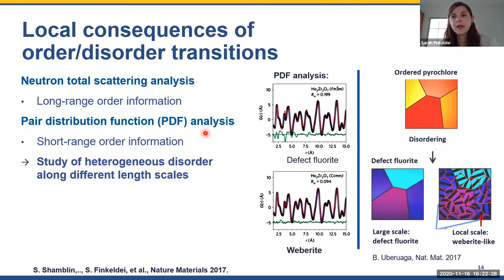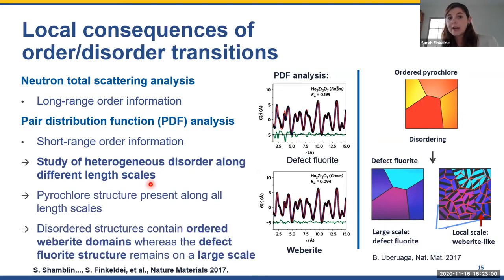So what we do when we look at this part is we are analyzing the diffuse scattering that we are collecting. And this provides information about the short range order of the material. And we looked at a pyrochlore sample and a defect fluorite sample with neutron total scattering analysis and with the pair distribution function analysis. So this basically enables us to study the heterogeneous disorder along different length scales.